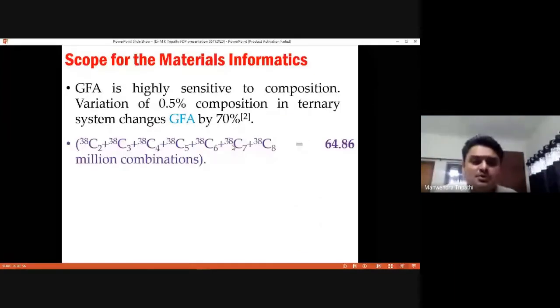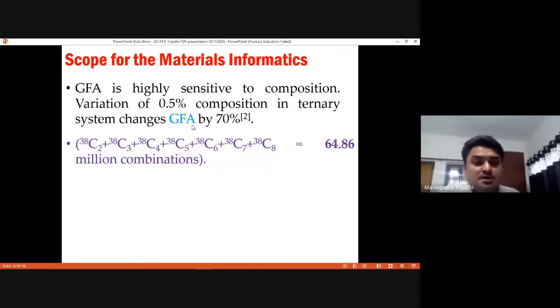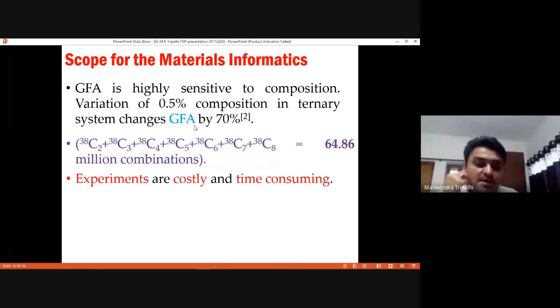So it is noted that glass forming ability is highly sensitive to the composition variation. For example, 0.5% compositional variation in a ternary system, the GFA has changed by 70%. I am referring a PhD thesis to supplement it. That GFA is very much sensitive to composition, first, and second is how many compositions are possible, right? For example, if you are taking 38 elements, for binary systems you will have so many combinations, 38C2, 3-component system, 4, 5, 6, 7, 8, and if you sum it, it comes out to be 64 million combinations.